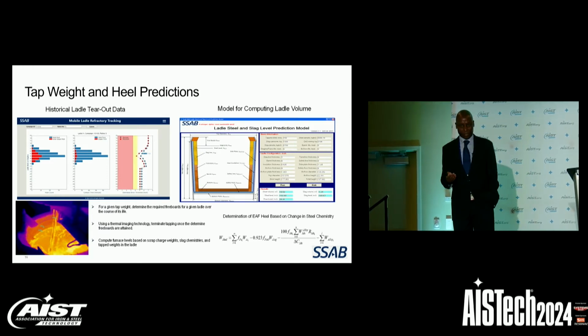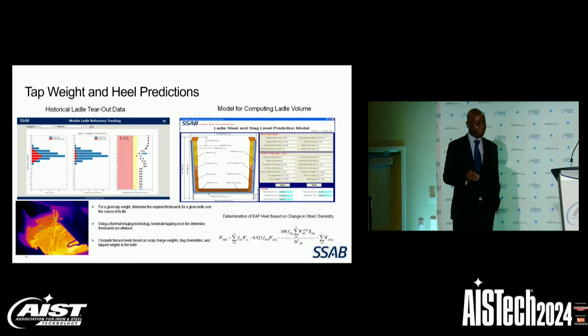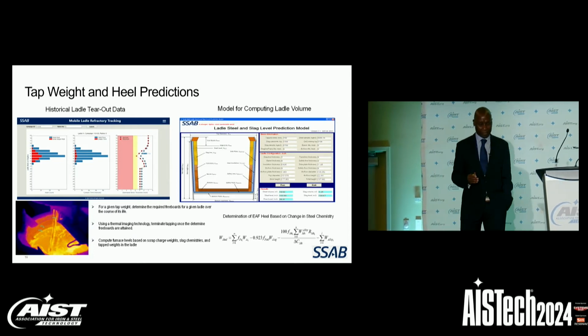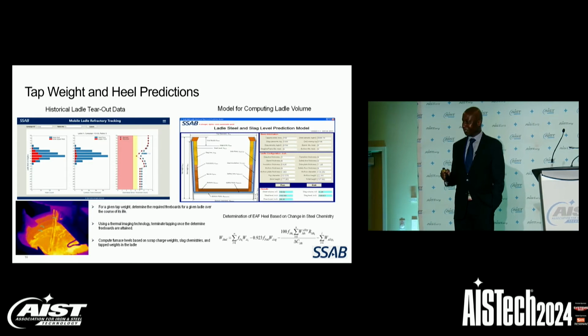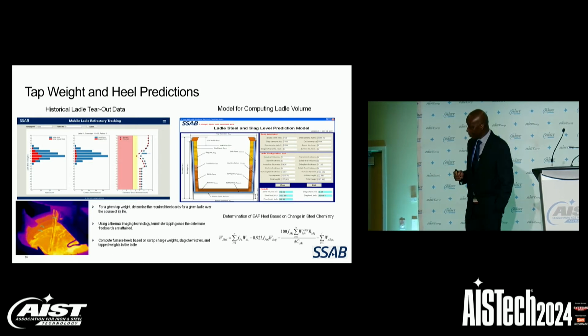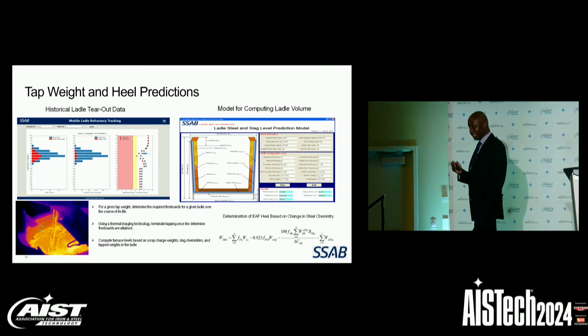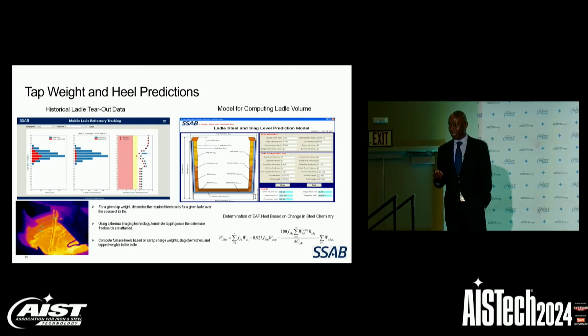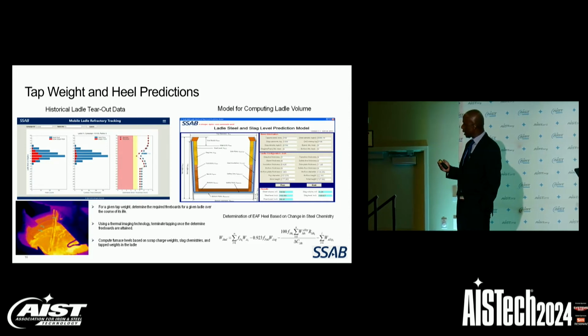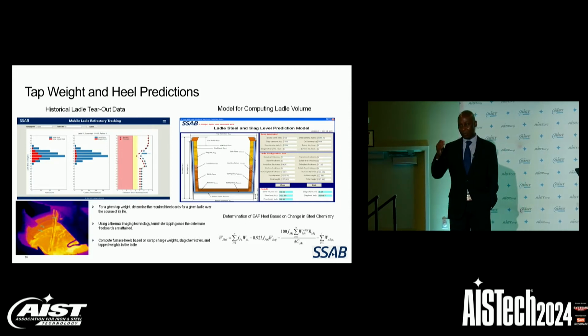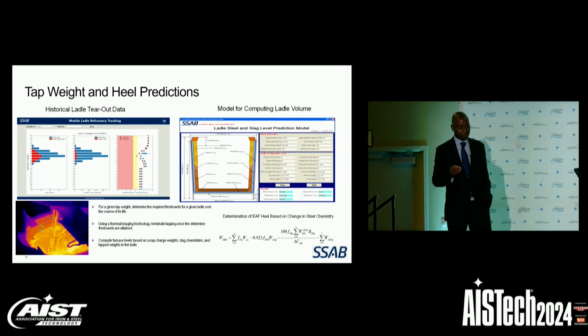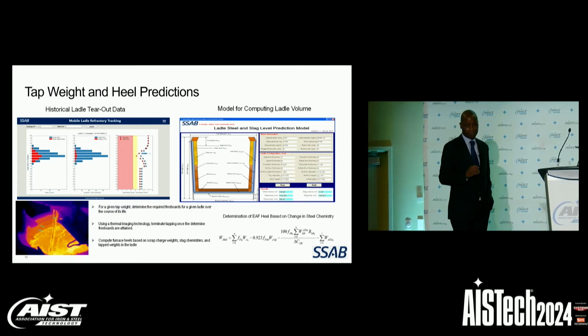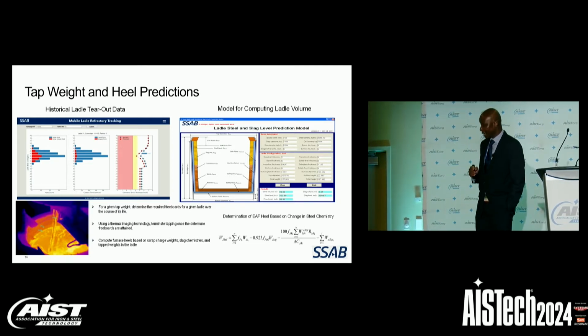So our approach is actually to measure the change in ladle volume during its campaign. The ladle does change its volume during this campaign because the refractory wears out with time. So by looking at historical data on refractory tear out, we developed a mechanism for measuring the profile of refractory wear in the ladle. Hence, we're able to calculate the ladle volume at any given time.